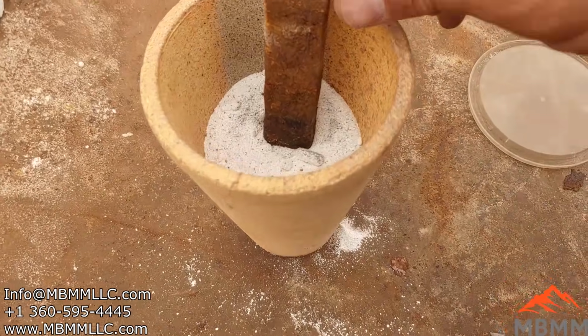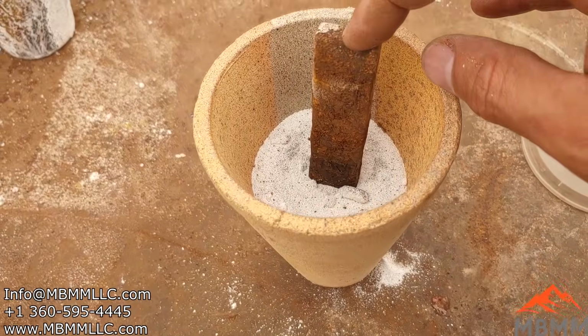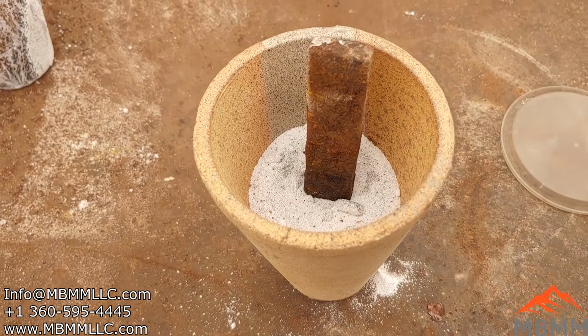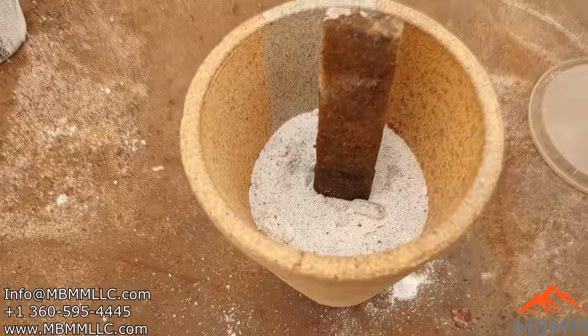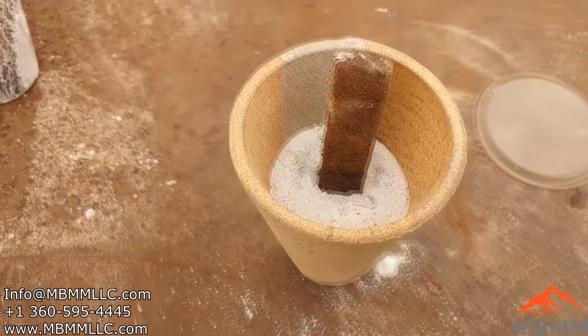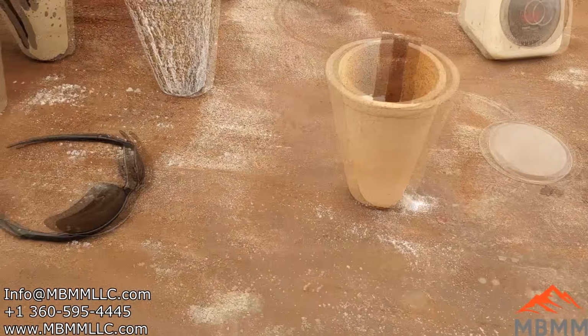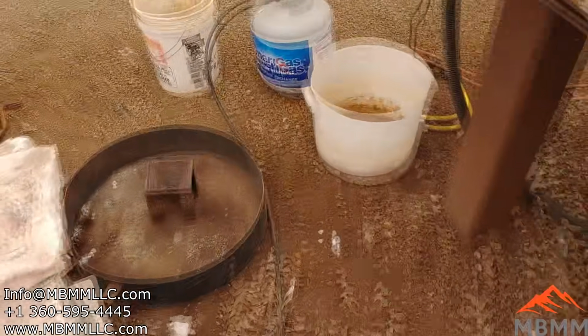Okay, here's our crucible. I'm going to use just a big, huge iron bar so we can get a lot of surface area for the iron and have a lot of iron in there available to pull off that sulfur from the lead.